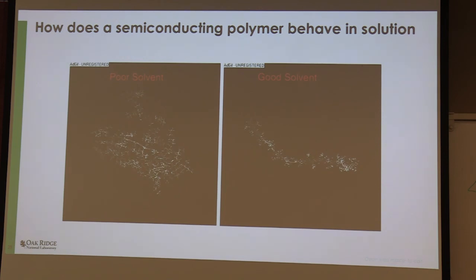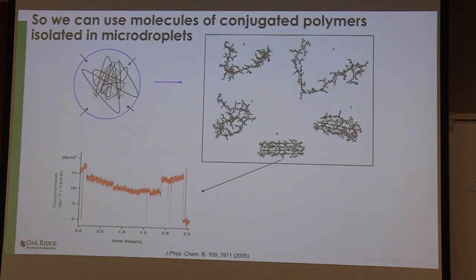This is a conjugated material, so the electrons are delocalized across the entire backbone of this system. When this folds up into this little stack, they connect together, and it looks like a single dipole, even though it's a huge molecule. That's interesting because you can use that as a quantum dot, even though it's a piece of plastic. That's freaky weird, right? And we showed that. We developed an experimental technique to take that, put it in a bad solvent, as predicted from the calculations, and make a single-molecule drop of that stuff. And when you look at the photoluminescence of that drop, the lifetime of that photoluminescence goes on for hours.